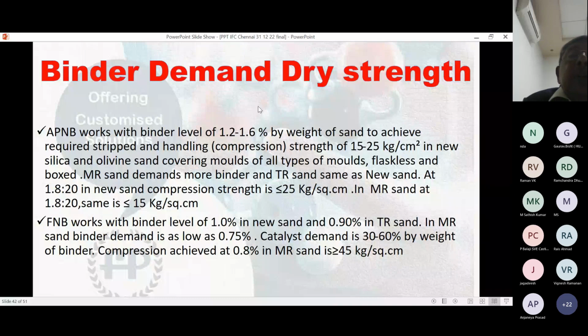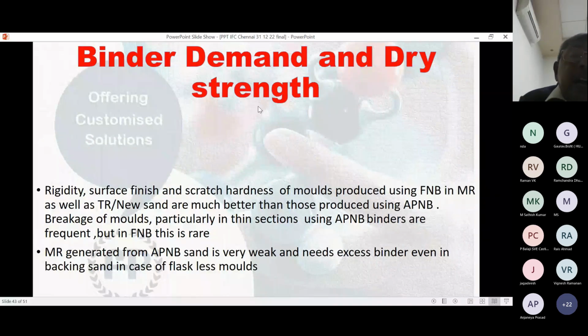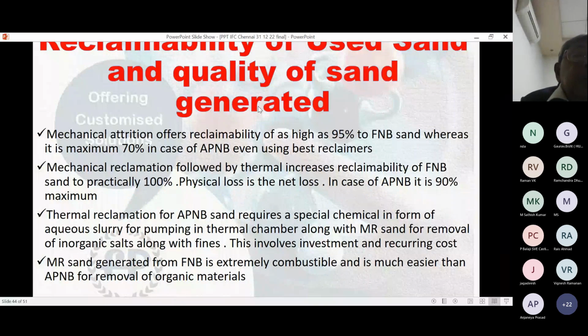So this I have already discussed: mechanically reclaimed sand for Alphaset is very weak in bond formation. Even while using it in backing sand, you need to increase the binder content so that it does not spoil. Mechanical reclamation offers reclaimability as high as 95% in Furan, and 70% maximum in the case of Alphaset.